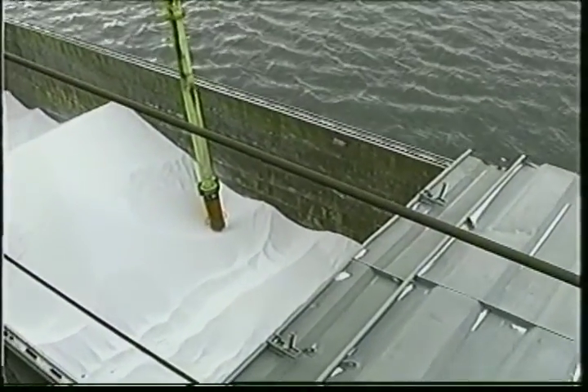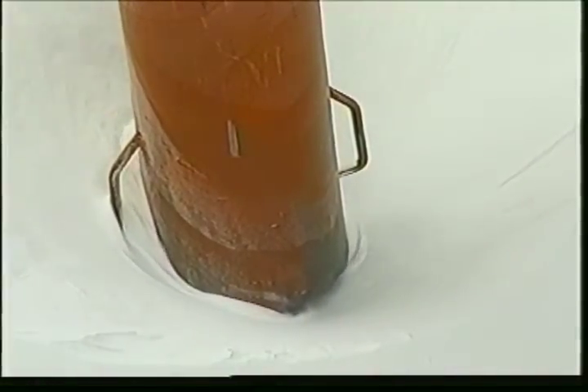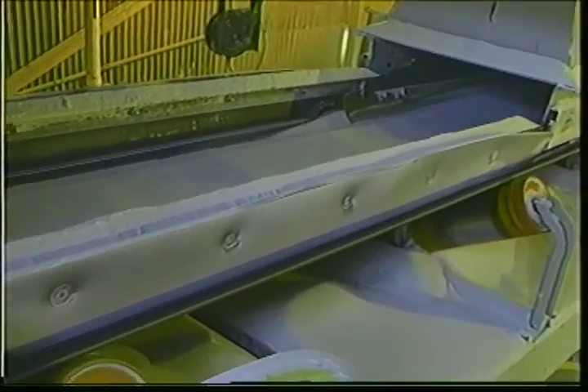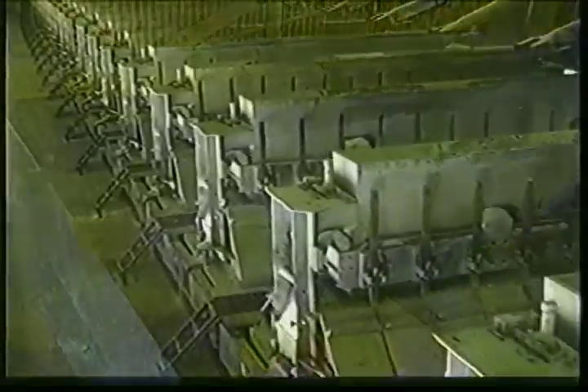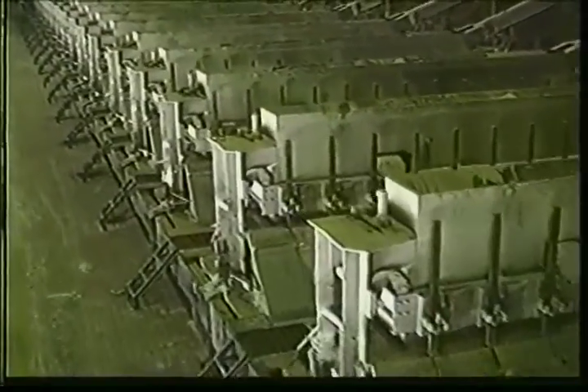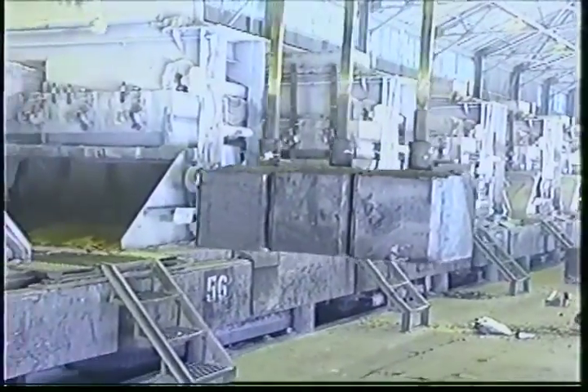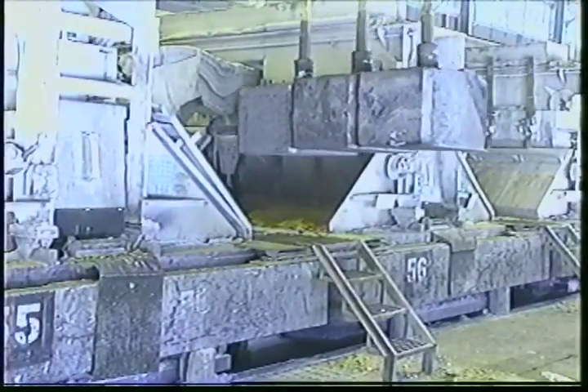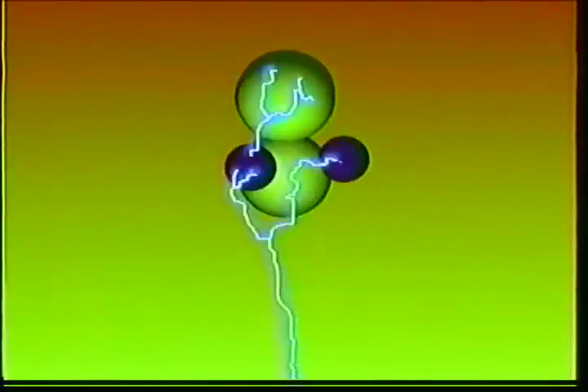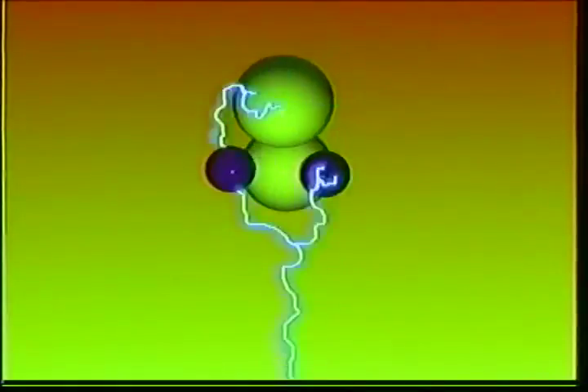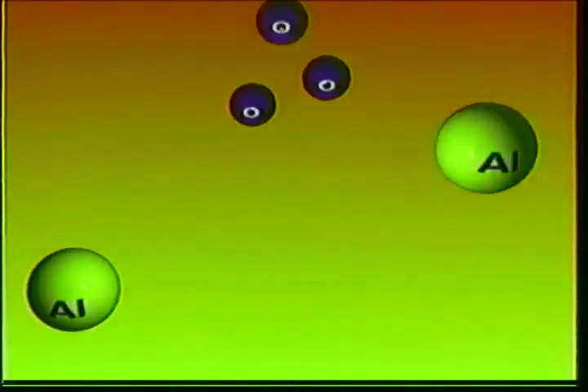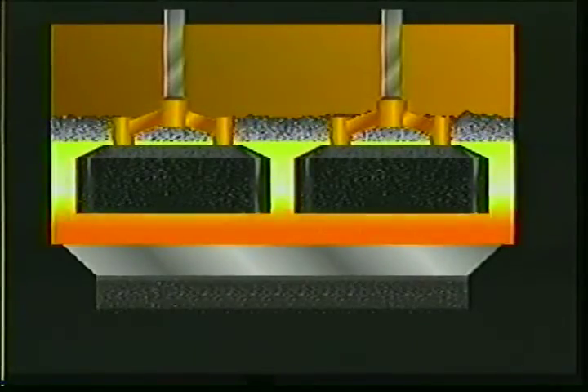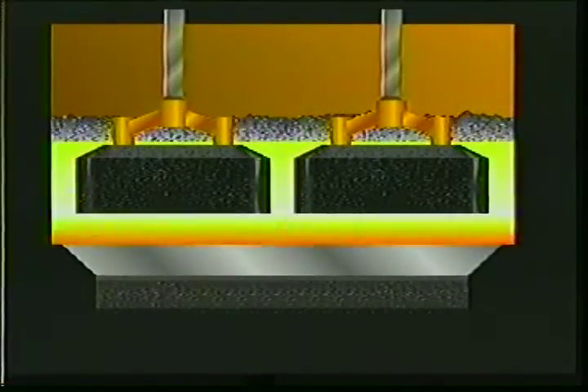Aluminum production begins at Warrick Operations when the refined alumina is drawn from barges. It makes its way through the unloading process and up the conveyor belt to the pot rooms, where the alumina is changed into pure aluminum metal in an electrochemical reaction. In these big electrolytic reduction pots located in the pot rooms, alumina is dissolved in a chemical bath solution at temperatures exceeding 950 degrees Celsius. Over 129,000 amps of electric current pass through the solution and separate the aluminum from the oxygen molecules. Once separated, the heavier aluminum sinks to the bottom of the pot. Each pot is capable of producing over 2,100 pounds of molten aluminum daily.